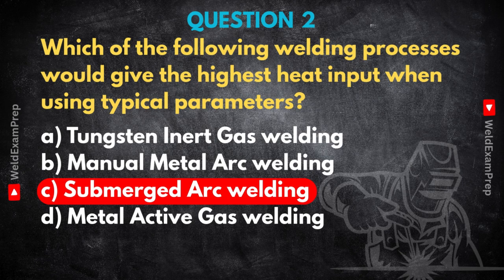That's a really crucial point. High heat input is great for productivity, yes. Deep penetration, high deposition rates. But metallurgically, it can cause problems. You can get larger grains in the weld and in the HAZ, the heat-affected zone. Larger grains often mean lower toughness, more risk of brittle fracture. It can also mess with the microstructure in alloy steels, maybe reducing corrosion resistance, or worse, leading to cracking, sometimes delayed cracking.